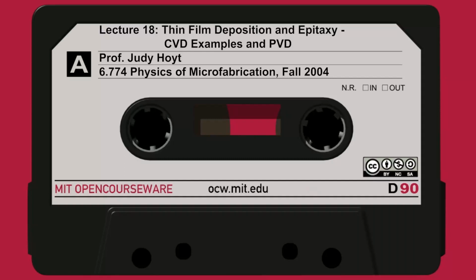Much more common these days, though, is reduced pressure deposition of epitaxial silicon. We talked about that. Here, the deposition temperatures are lowered significantly compared to atmospheric pressure, and people can deposit epitaxial silicon typically all the way down to 750, maybe 700 even, in the reduced pressure systems. Besides silane, we also talked about silicon tetrachloride being used. Also, trichlorosilane shown here, and dichlorosilane, probably one of the most common gases, is used for selective epigrowth.